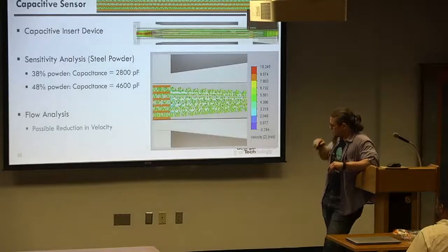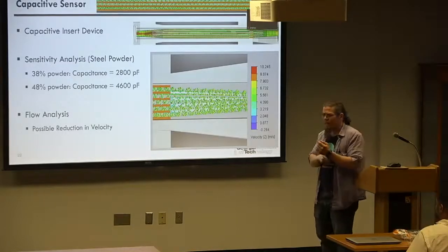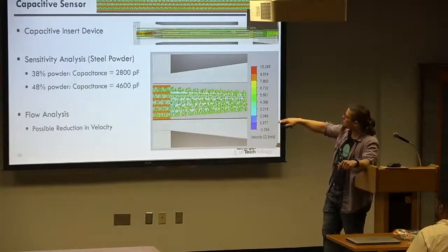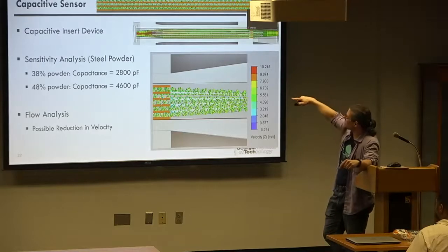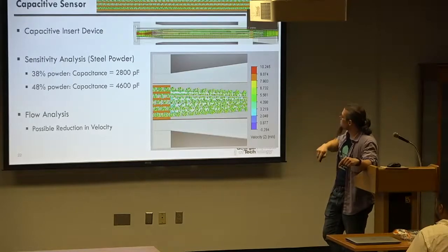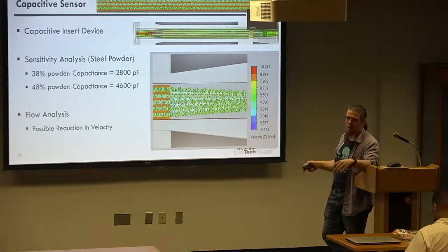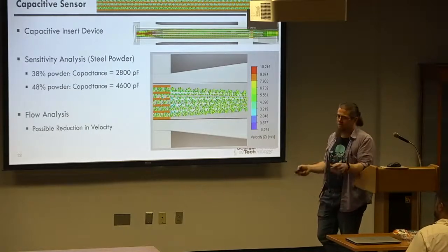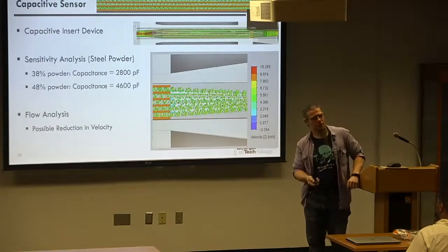Flow analysis. We considered a possible reduction in the velocity when we ran our basic flow analysis. You can see that up here. There's a minor dip in the flow velocity. We actually then printed the part, stuck it in, and checked. Does the powder slow down? Does it fall out of entrainment?